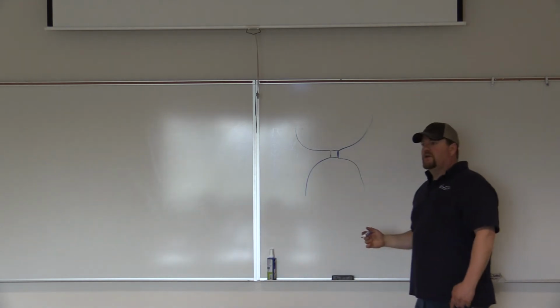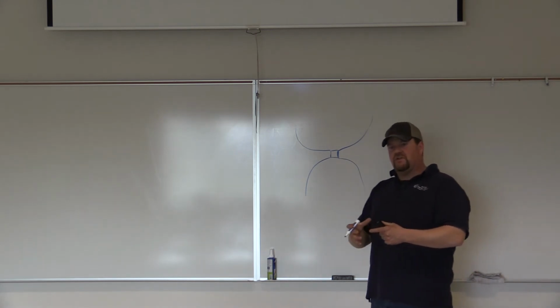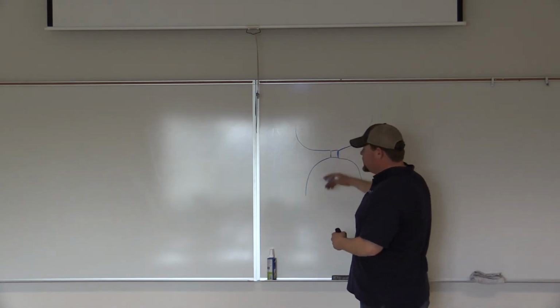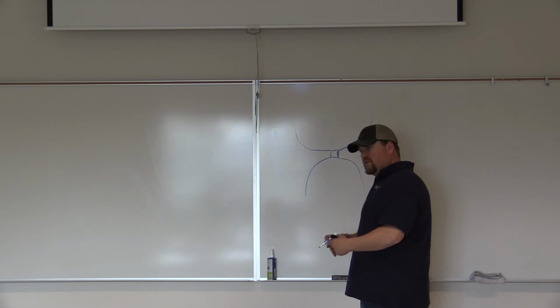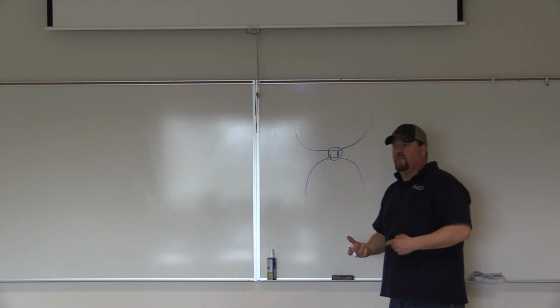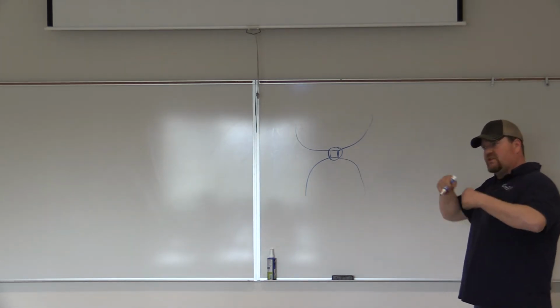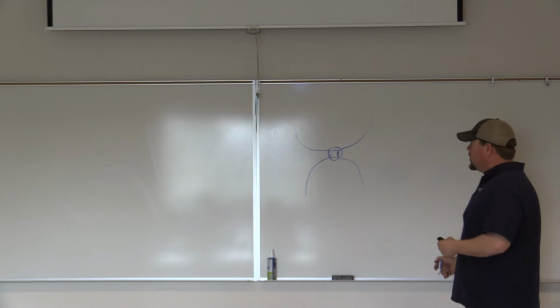Okay? So your insert pieces here, it's naturally built in as a 3/32 spacer. It's consumed into the weld. You stack that in there, and it's considered a spacer or an insert. Stack that in there, and basically you don't use anything for your filler metal. That is your filler metal for the first root. It makes it much easier, so you're not doing this, and guaranteeing penetration.